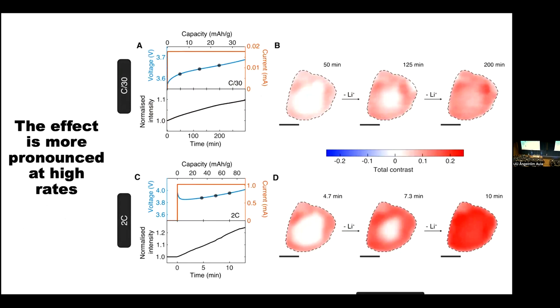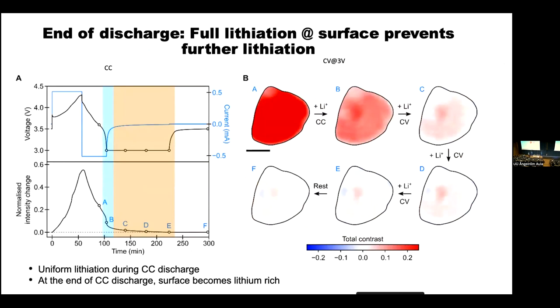And just to check that we're not totally mad, if you go to higher rates, these phenomena get more pronounced, again suggesting this is a metastable kinetic phenomenon. And at the end of discharge, you can put the lithium in, but it really takes a long time.